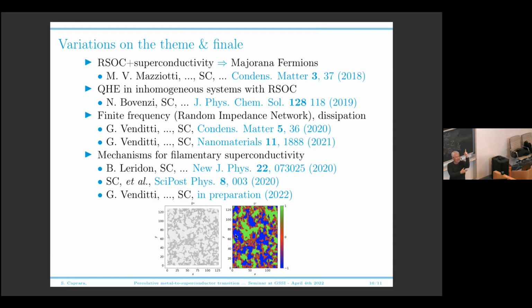Now, how can you turn a spin up into a spin down across a domain wall? The only way you can do that topologically is that the spin rotates so that at a certain point, the spin is in the XY plane. But this is superconductivity. And we can measure the superfluid response that it is finite. So the red domains are superconducting domains. And they are very filamentary. So this is a very simple realization of the idea we have in mind.